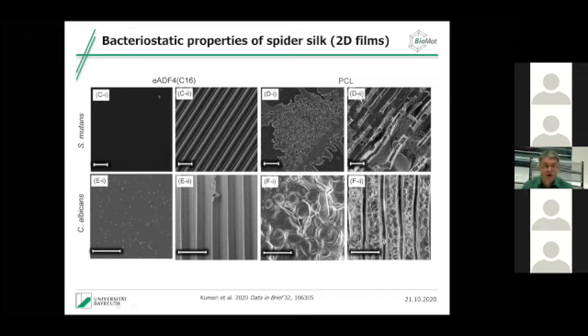And here you see one of our control materials, which is polycaprolactone, a very often used polymer in biomedical applications. Here we tested bacteria like Streptococcus mutans, and down there we tested a yeast, Candida albicans. And as you can see, nothing is growing on the silk surface, no matter if it's a flat surface or a structured surface. In contrast, on the polycaprolactone, you see huge areas covered with bacteria or with yeast, and this is what we call a biofilm. So we see biofilm formation immediately after a few days.